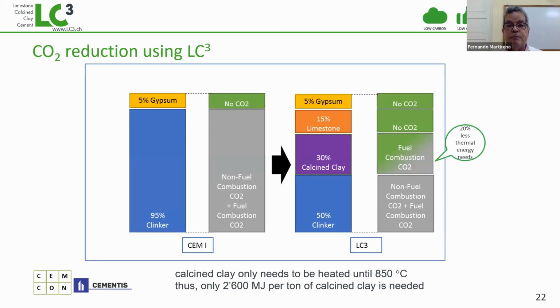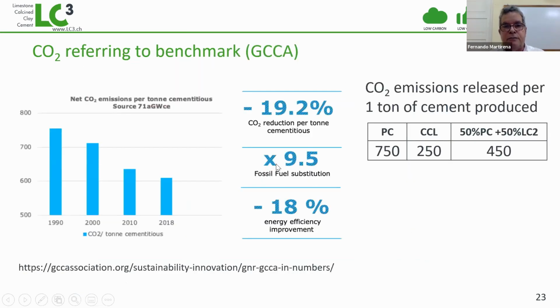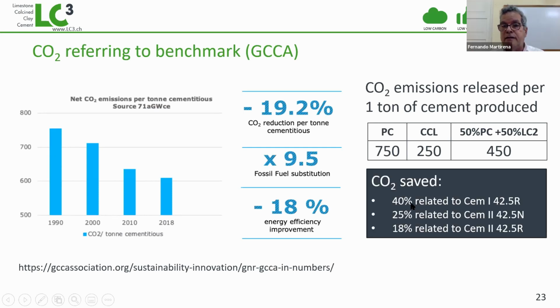In terms of CO2, again, remember 60% of the carbon emissions associated with cement production are associated with the decarbonation of limestone, which is 80% of clinker raw materials. So if you replace clinker by any material, you're automatically reducing carbon emissions. Of course, here we are calcining the material, so we have some collateral CO2 emissions associated with the fuel. But when you check this and you make this analysis, for instance, here I'm taking the Global Cement and Concrete Association benchmark figures, where it's a fully optimized cement, and you compare here the CO2 saved.